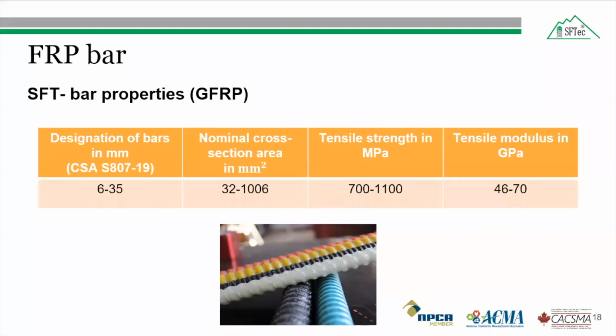The second point is that fiber reinforced polymer bars are lightweight, non-conductive, and magnetic free. The properties of the glass fiber reinforced polymer bar available at SFTec are the following. The bar diameter generally varies from 6 mm to 35 mm, which have a nominal cross-sectional area of 32 to 1006 mm square. The tensile strengths depend on the bar type, whether it is classified as bar 1, 2, or 3, based on the CSA S807 code. And the lower value of the tensile strength corresponds to the lower value of the tensile modulus or elastic modulus,